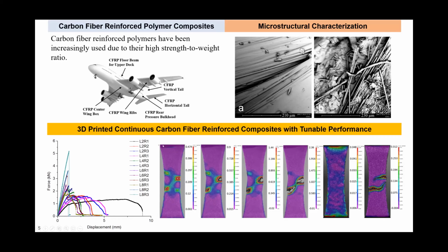And from these DIC images, for the first 2 DIC images, you can see we can observe crack initiation, crack propagation, and eventually failure. And this is a more ductile composite. For the last 2 DIC images, this one is more brittle. So in other words, the failure basically happened almost all of a sudden, which is a more brittle property. So again, by varying the continuous carbon fiber amount, the volume fraction, we can further tune and tailor the mechanical properties of 3D printed continuous carbon fiber reinforced composites.